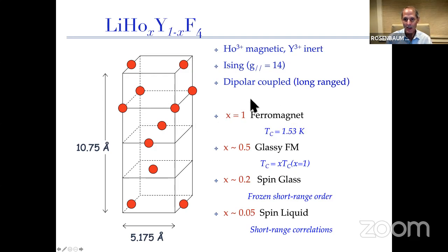So if you have a pure system, that is all the sites are occupied by holmium, lithium, holmium tetrafluoride, then it's not obvious from the beginning what the ground state should be because of the dipolar interaction admitting both ferromagnetic and antiferromagnetic interactions. So of course, two dipoles like this on top of each other order ferromagnetically, two dipoles like this order antiferromagnetically. But it was shown many years ago by Luttinger and Tisza that basically the first nearest neighbor, which is here, dominates the ground state. So this is a ferromagnet. The first nearest neighbor coupling is ferromagnetic. Second nearest neighbor is antiferromagnetic. But the problem we will have is we're going to have a mix of ferromagnetic and antiferromagnetic bonds competing.